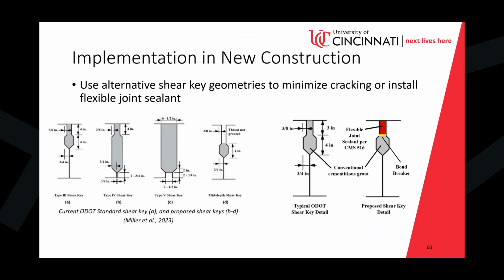So, for example, this is again the idea of the longitudinal joints, and the image on the far left again is that shear key detail that we're used to seeing. But from that NCHRP report, these images B, C, and D are proposed different shear keys that they found to be more effective. Ones that have a larger area, bond area, more grout, they found those wouldn't crack as much. Or moving the shear key down to more of the mid-depth, they found that wouldn't lead to as much cracking.